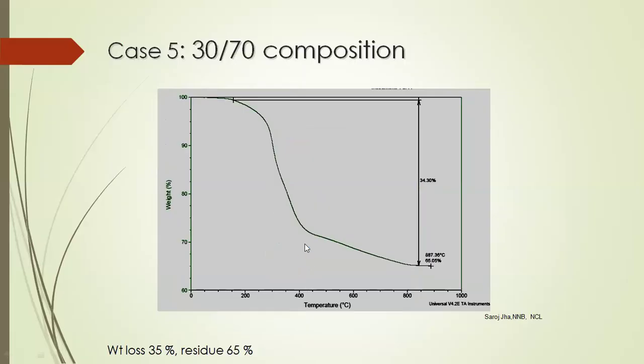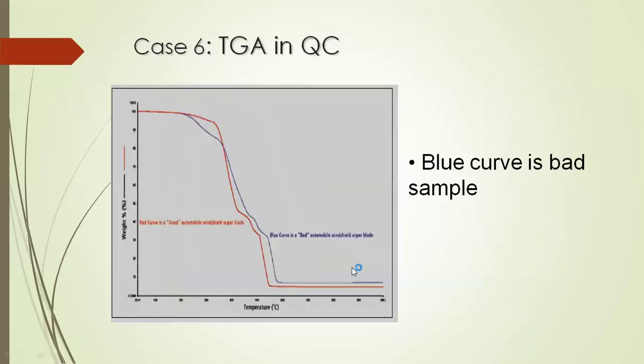In case of polymer blends, you can find out what blend composition is there, similar to the filler content. Then, as I told you, you can use TGA in QC also. This red is a good sample and blue is a bad sample. When you just do a simple TGA, which is otherwise similar, except in the onset of degradation. See, my bad samples are degrading far below my good sample, and that's why it failed in the QC. You can use TGA in the QC also. Quick sample,